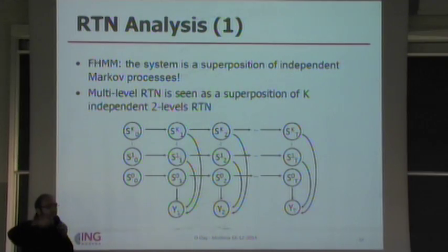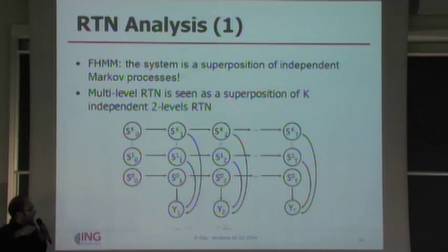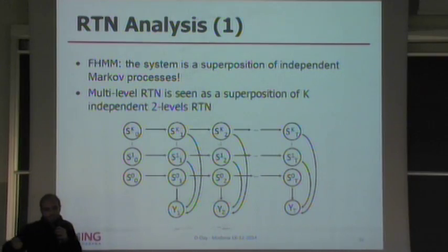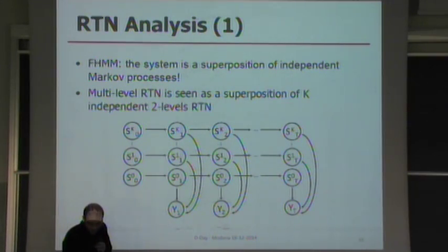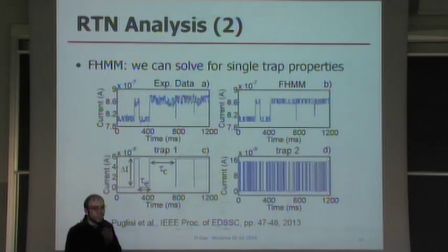Each chain represents a 2 levels fluctuation. So this is the state of the first chain. It can either be 0 or 1. This can either be 0 or 1. This can either be 0 or 1. We can have up to k chains. So the combination of their states is related to the current that we see. So by modeling the system hidden behind the RTN this way, we are able to do this.